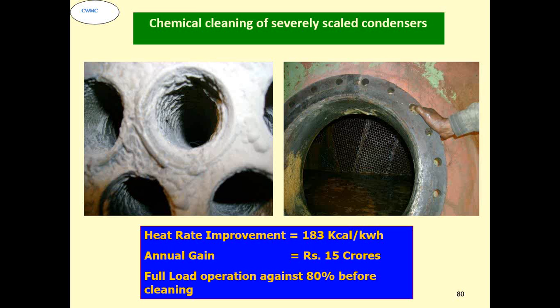Now this was a case of condenser scaling, where calcium carbonate scale was there. The tubes had so much scale, the plant was losing heavily. They were not able to run the 210 megawatt unit to more than 150 megawatt, and their vacuum and everything was dropping. When we checked, we were not able to put our fingers inside the condenser tube. So much thick scale had formed. So we chemically cleaned it, and what we gained out of that was almost 15 crore per annum. The plant gained, and they were able to operate the units at full load even during the peak summer.